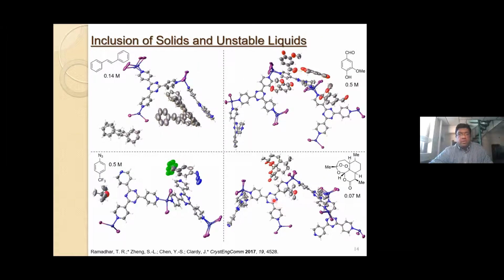And I was able to include a variety of compounds inside. So not only E-stilbene, I was able to put in vanillin, 4-trifluoromethylphenylazide, and this is not a solid, but it is a liquid inherently, but phenylazides don't tend to be that stable, and you don't want to have it concentrated. So, solubilizing it in MTBE, we were able to put it inside the crystalline sponge and observe its structure. And this is my favorite example where we were able to include artemisinin, which is an anti-malarial drug and was the subject of the 2015 Nobel Prize in Physiology or Medicine. And at a 0.07 molar concentration, I was able to observe this inside of the crystalline sponge and was able to determine its absolute configuration.